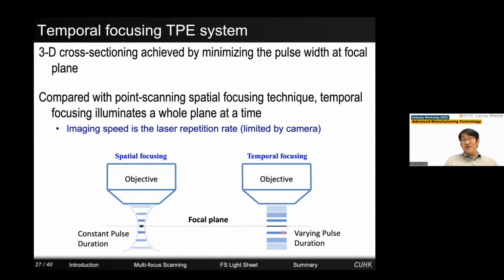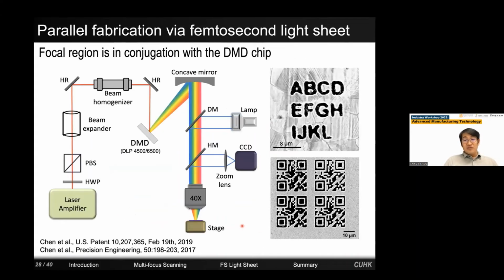In order to use this for fabrication, we have to generate specific patterns on the light sheet, right, in order to perform fabrication. So that's where our contribution came in. We replaced the optical grating with a digital micromirror device. As I said, DMD is a blaze grating with an angle of 12 degrees. So by selecting the proper diffraction order in an experiment, the -5th order diffraction, we can achieve high laser efficiency, around 50%, and implemented temporal focusing.